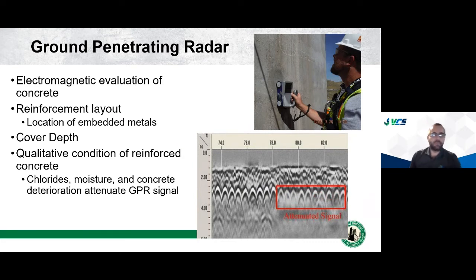So why is that? Well, the signal strength from that reflection is weaker, and so that's a sign that there may be some deterioration there. Things that will affect the GPR signal: if there's a lot of chlorides and moisture in the concrete, that'll weaken or attenuate the signal. If there is a lot of concrete cracking and deterioration, that'll attenuate the signal as well. So there's a lot of things associated with concrete deterioration that'll attenuate the signal.